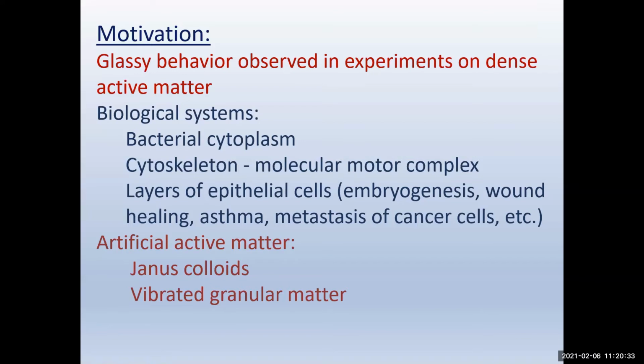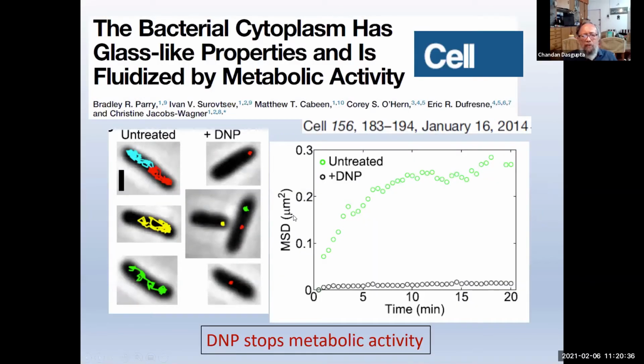Yes. So let me show a couple of examples of this biological active matter, which shows glassy behavior. As I said, the bacterial cytoplasm has glass-like properties. This paper came out in Cell a few years ago. What they did is they looked at tracer diffusion inside a cell, and when the cell has metabolic activity, the tracer basically goes through the whole volume. As you can see here, these are the tracer paths, and it explores the whole cell. But then when DNP, some chemical that stops metabolic activity, is added, the tracer doesn't diffuse anymore. You can see here, the tracer is basically undergoing what is known as cage motion, in the sense that it's just vibrating about some equilibrium position with a small amplitude.